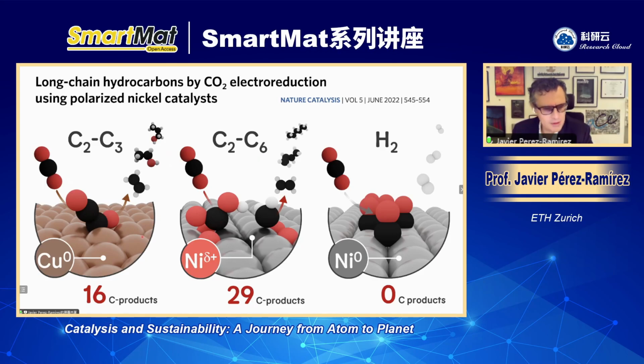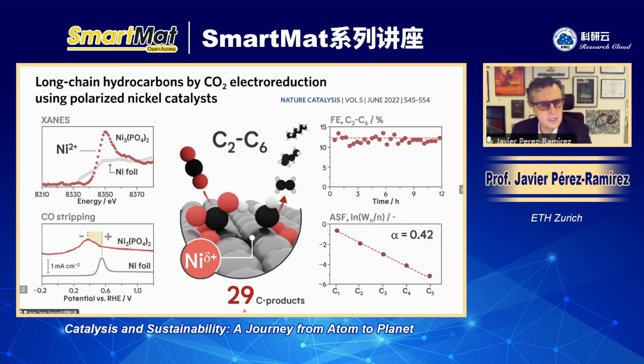Not only that, we are much more promiscuous in the product distribution. Instead of 16 products, we have been able to make 29 products. That means there is new chemistry beyond copper for electrocatalytic reduction of CO2. The reason for this we attribute to the fact that when you have nickel phosphate compared to metallic nickel, you always have a signal of polarized nickel, which stays upon use of the catalyst. So this catalyst is very stable.